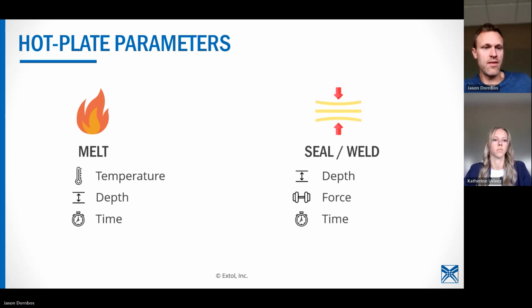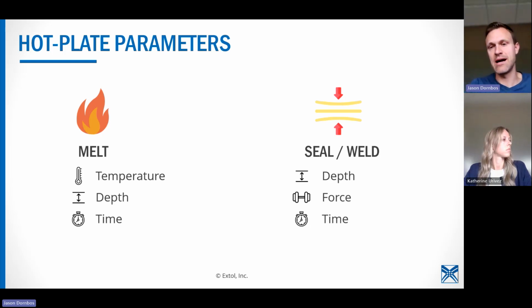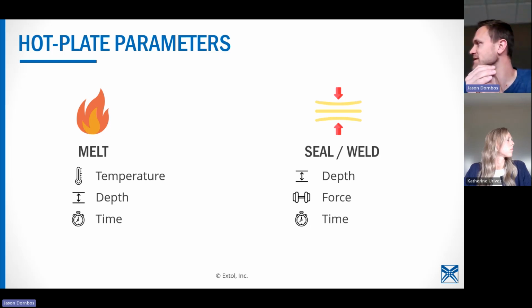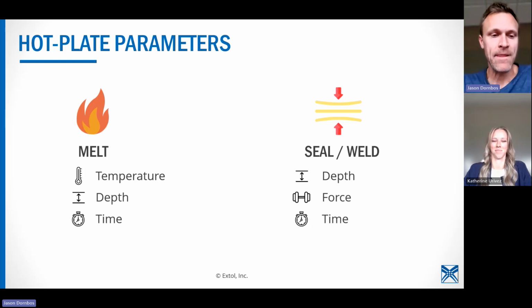There are several different parameters that you can use to affect how much heat and how much pressure you're applying, and you balance those two things to get a good weld. On the melt side, we can control the temperature of the heat plate. Typical heat temperatures are 450 degrees on the very low end, and then upwards of 900 degrees Fahrenheit. So you can get very, very hot tools, or tools that are much cooler relatively, though you're still going to burn yourself.